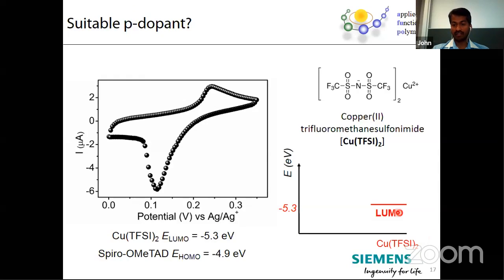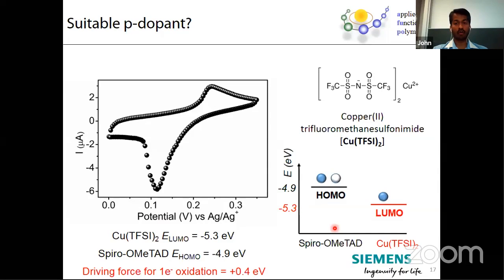And here is the copper TFSI LUMO. We did the same for spiro-OMeTAD to understand where the HOMO of the spiro is located. In that case, we found that the spiro is located around minus 4.9 electron volt. Of course, this is negative, so minus 4.9 lies a little higher than minus 5.3. So now you see that the HOMO is lying higher than the LUMO of our copper TFSI system. In this case, there is a possibility for an electron transfer from HOMO to LUMO very easily, because we have a driving force of about 400 milli-electron volt. The higher the difference between the HOMO of your matrix and the LUMO of your dopant, the better the oxidation process would happen, or the higher the yield of the oxidation process, we put it that way.